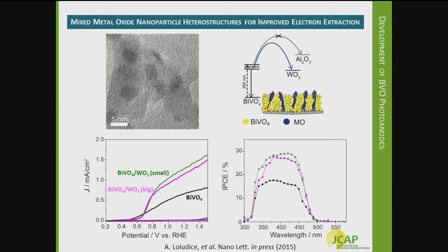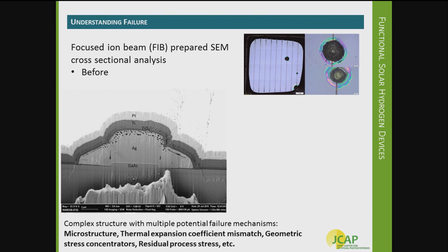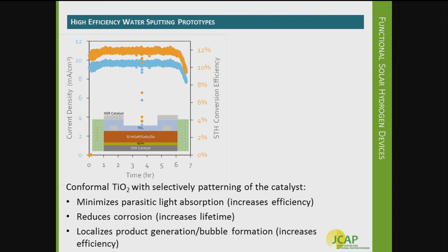As for the catalyst, this was operated under 1 molar sulfuric acid. I believe it was a mesh, with iridium oxide coated on that mesh. This is a follow-up question. So what is the current of that device? That was a device, I won't say it's exactly the same device, but it's in the exact same class of devices, at a current density between 9 and 10 milliamps per square centimeter, which corresponds closely to approximately 12%.